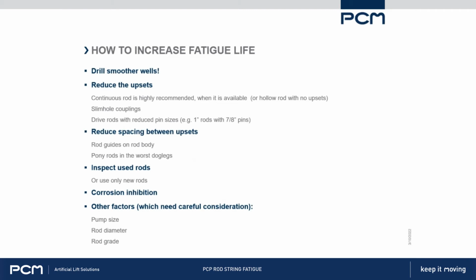If they have straight fins on them, you don't want to be rotating a rod with straight fins on it. Straight fins are fine on the spin-through type couplings because you want it to stay stationary against the wall. But if it's going to rotate with the rod, like a molded-on guide, you'd like to have either something round on it, so either spiral or just a round body. But yes, reducing the spacing between the couplings goes a very long way towards reducing that effective curvature. And generally, even one guide will often be enough to solve a fatigue problem.